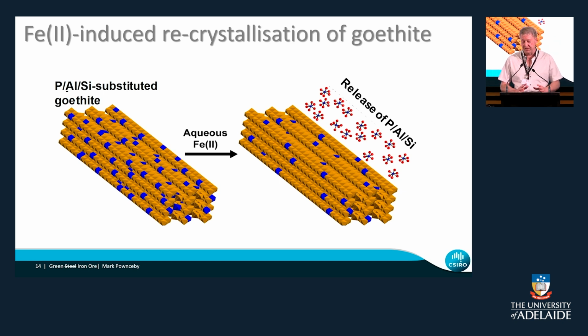And the way this process will work, instead of actually leaching the ore itself, what we do is a goethite recrystallisation. So if you imagine when the goethite is forming, you've got fluids that are rich in phosphorus and aluminium and perhaps silicon, and then it crystallises a goethite which contains all of those elements. So here we're trying to reverse it. We're trying to recrystallise the goethite and actually eject the impurities. And there's certainly some promising work that we're doing around that we think might be very good in the future.